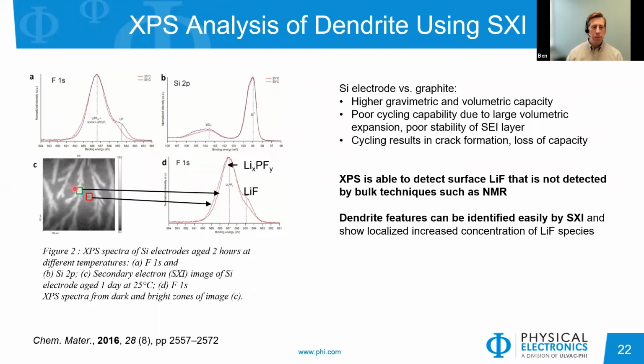And we can choose points on and off of that to see what the chemical differences are. In this case, what we do find is that there is more of a lithium fluoride type development on the dendrite area. And because of the surface sensitivity of XPS, this may not be detected by more bulk techniques such as NMR. So that is one of the nice features: both the ability to see this dendrite, to locate it easily with the SXI, and then to identify the chemistry differences between those 2 regions.